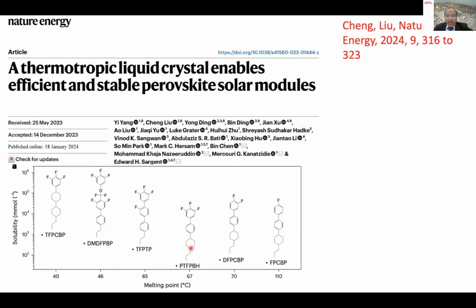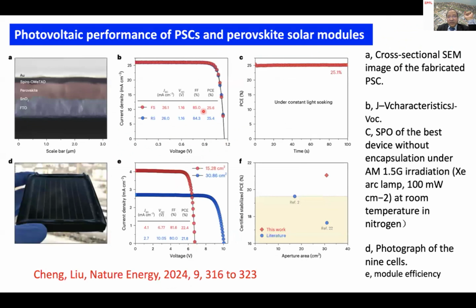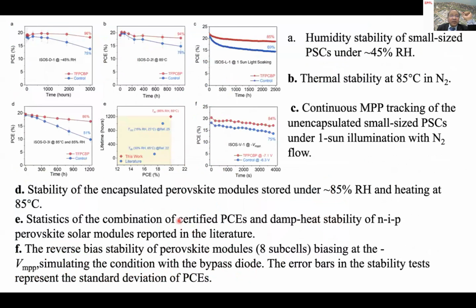So this approach has also given us very high efficiency, 25.6% in a small cell, and in a mini module, 22.4% efficiency. The most important phenomenon is the stability at 45 degrees, 45% humidity, and at 85 degrees temperature, 85% humidity. The stability is significantly enhanced. And on the bottom here is the module data.